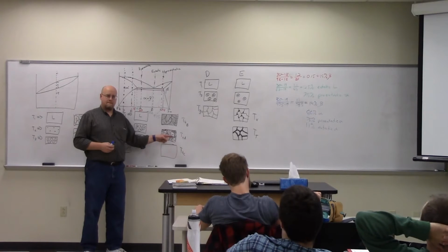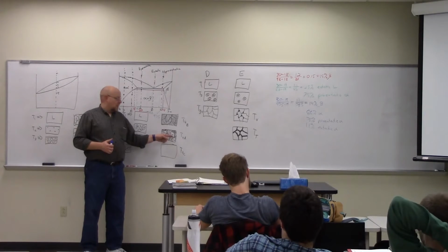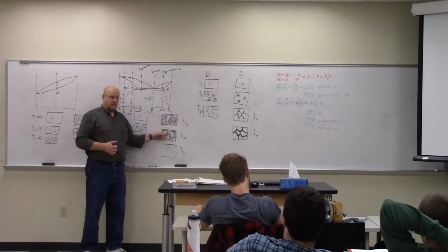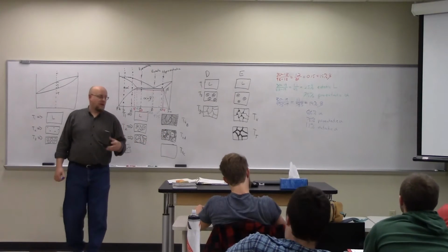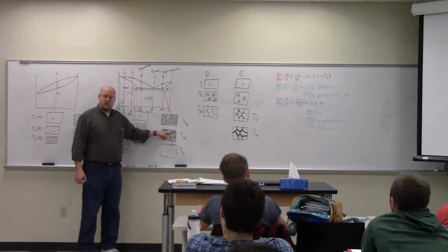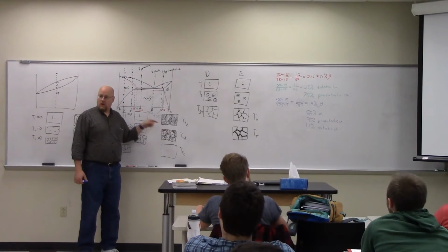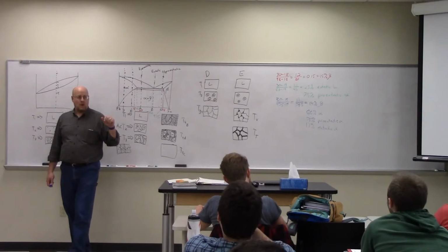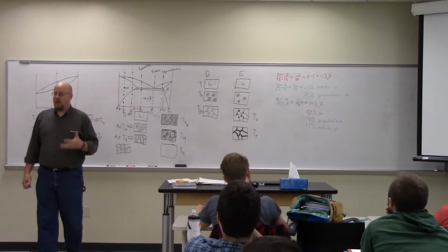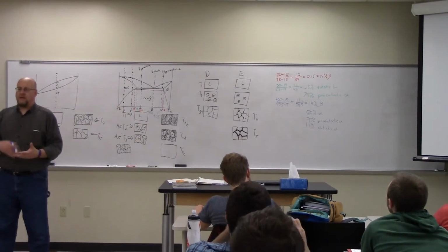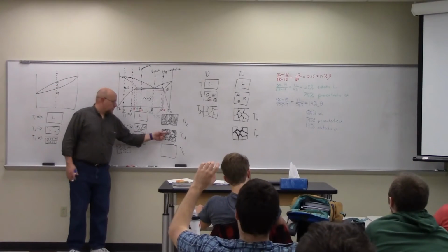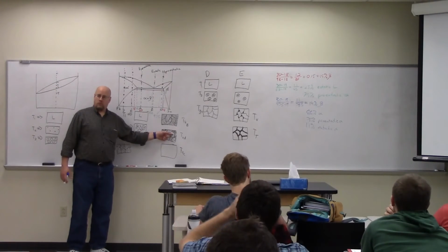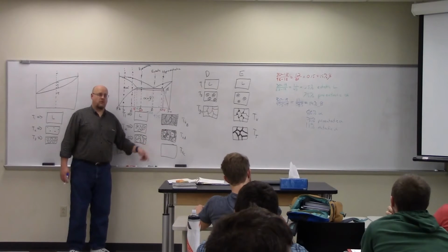See what I'm saying? And all my beta is in these slices, in the eutectic structure. And the reason that's important is because this stuff has different mechanical properties than this does. Pro-eutectic alpha has different mechanical properties than eutectic alpha, or the eutectic microstructure. The pro-eutectic grains have different properties than the eutectic grains.